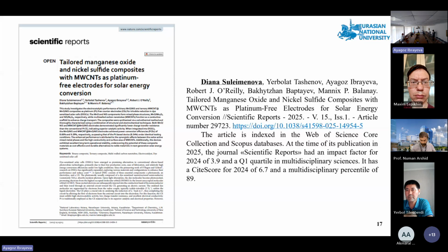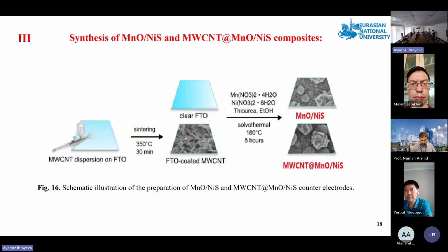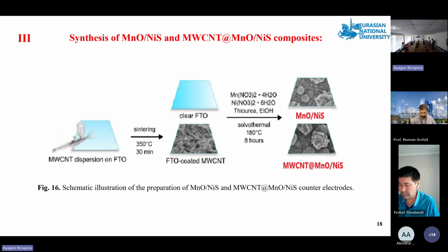According to the third provision, we published a research article in the journal Scientific Reports. We synthesized a ternary composite, manganese oxide and nickel sulfide with multiwalled carbon nanotubes, in 2 steps. First, we take multiwalled carbon nanotubes, spray them on the FTO substrates, and heat. The next step, we take the multiwalled carbon nanotube coated substrates and place them in an autoclave with chemical precursors, manganese and nickel nitrates with thiourea, heat, then wash and dry.